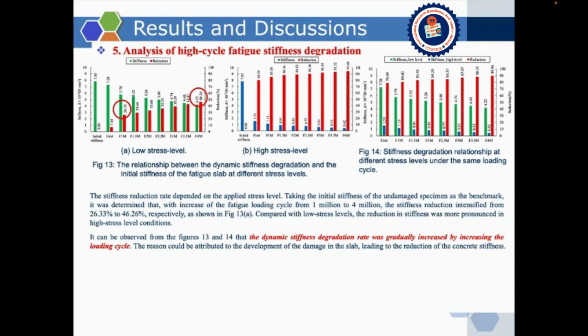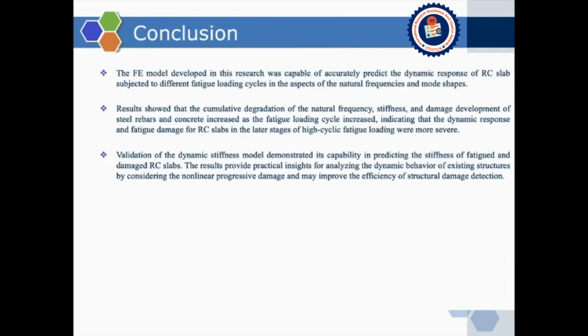It could be observed from the figure that the dynamical stiffness degradation rate gradually increased with increasing loading cycles. The reason could be attributed to the development of damage in the slab, leading to the reduction of the concrete stiffness. This part is about the conclusions.